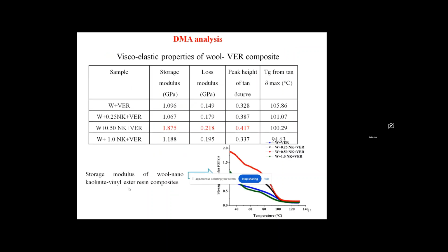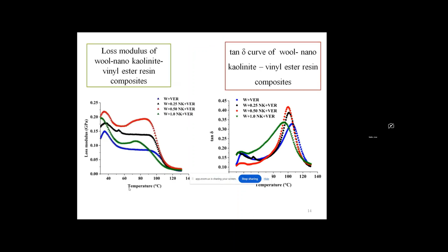Then again, this is the dynamic mechanical analysis, which indicates the viscoelastic properties of wool vinyl ester composites. So here the storage modulus was found to be highest at 0.5% addition of nano kaolinite. Loss modulus was also found to be highest. Accordingly, the tan delta was also found to be the highest in the wool vinyl ester composite having a composition of 0.5% nano kaolinite. So this is the respective graph of loss modulus and tan delta.